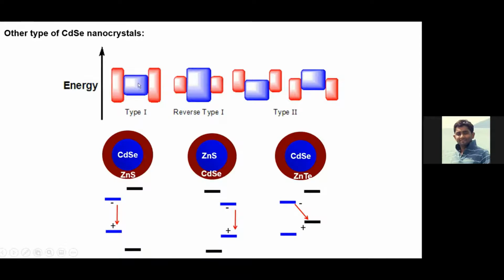That means in type 1, the center part, the core, is a smaller band gap material, and the shell is a higher band gap material. Like here, you can see the band gap is very high and small. So in type 1, your electron and hole are confined only in the core.